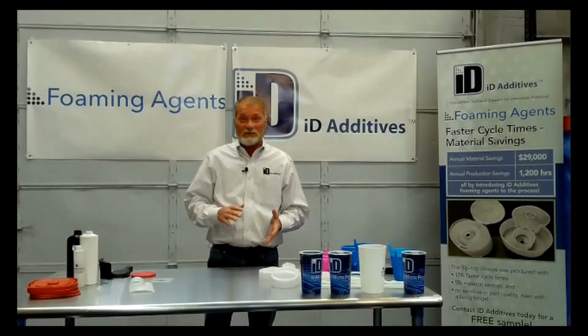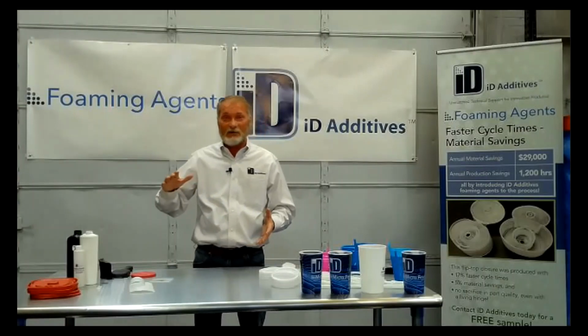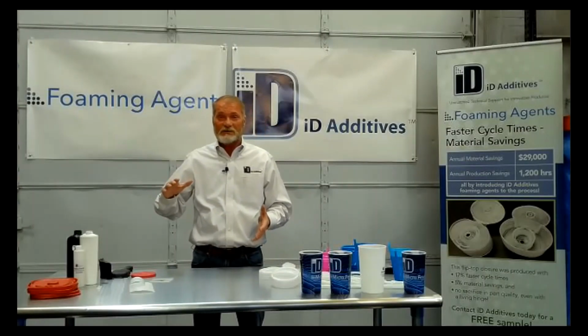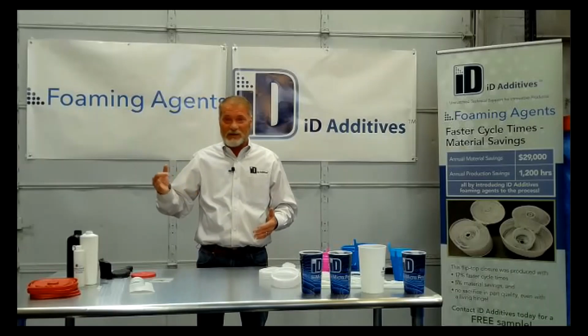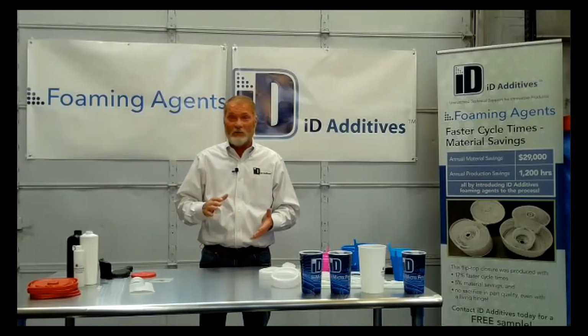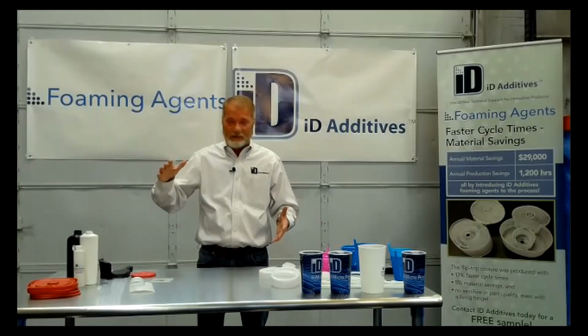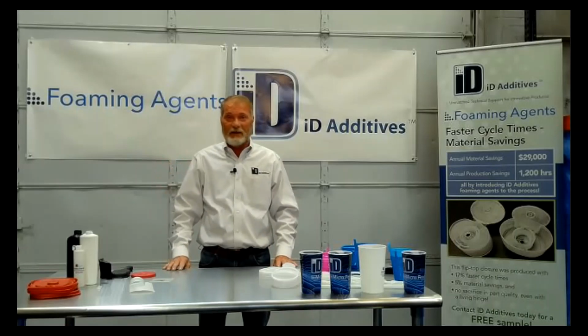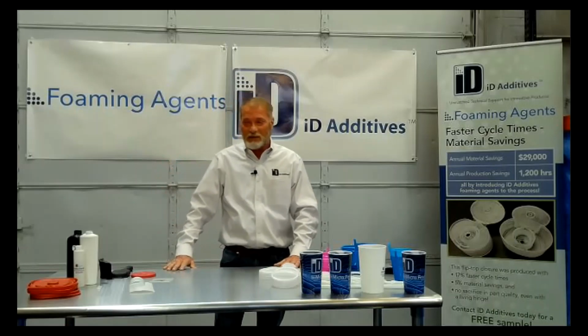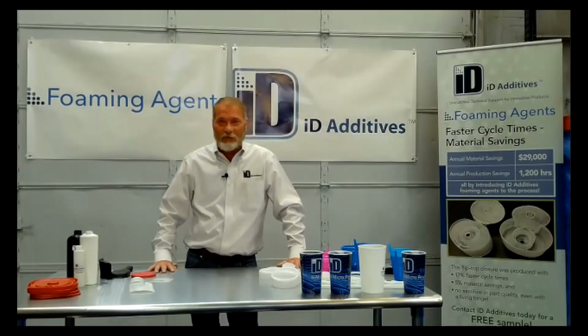So that 4% turns into a lot greater number when you consider that if it's 30% of any of those fillers, 70% is all you're going to be able to foam. 4% of 70%, if 70% was 100%, would be quite a bit bigger than 4%. So foaming agent can only foam the polymer. It can't do anything with the fillers.